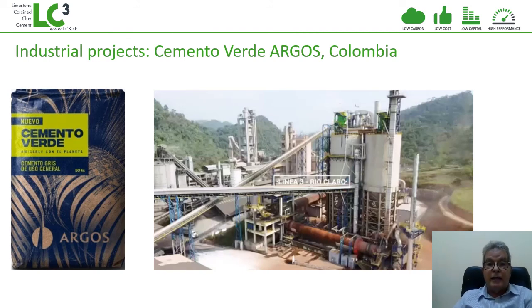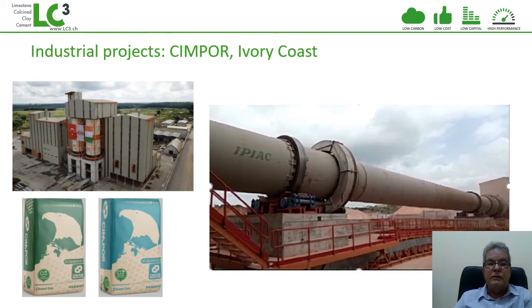This idea has gone out of the lab, and there are several companies already producing the cement at commercial scale. We have the example of Cemento Verde in Colombia, where they are producing using calcined clays very successfully, producing 1,500 tons of calcined clays per day. And also there's another factory in Africa, in Ivory Coast, that was organized by the company CIMPOR that also is producing cement containing a combination of calcined clays and limestone. In this case, 720 tons per day of calcined clay, 250,000 tons per year. Both are operating successfully and selling their products. So we're talking about a material that is now going mainstream.